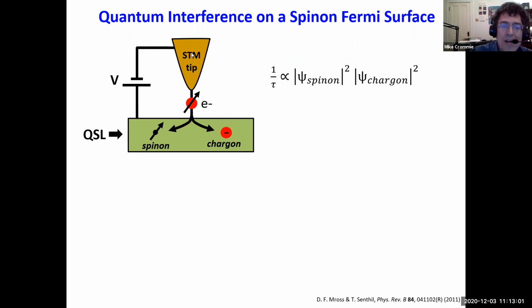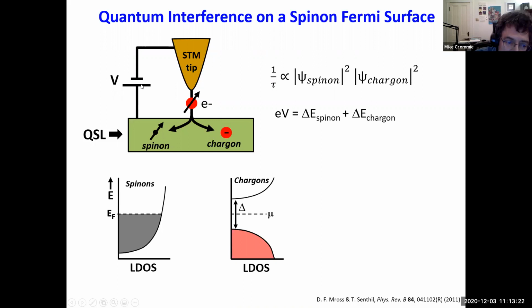So let's consider what happens when you tunnel the electron into the quantum spin liquid. As I said before, the electron has to break up into a spinon and a chargon. And so the tunnel rate is going to be the product of these two wave functions. So if I have a voltage on my STM tip, that means that the electron has a total energy of eV, and that energy has to be shared between the spinon and the chargon because they both appear when the electron tunnels in. So both of them have to get that energy.